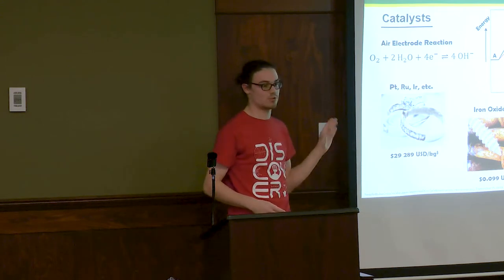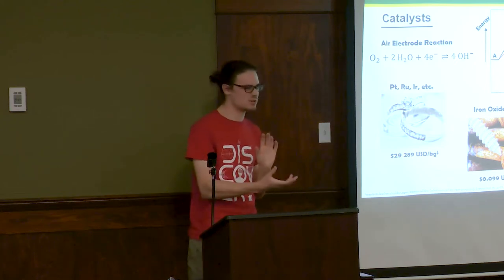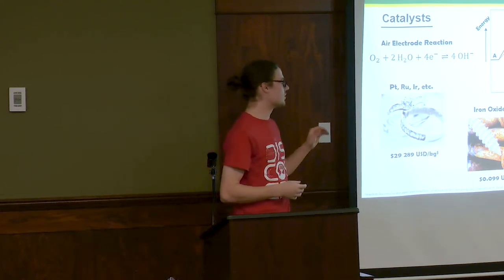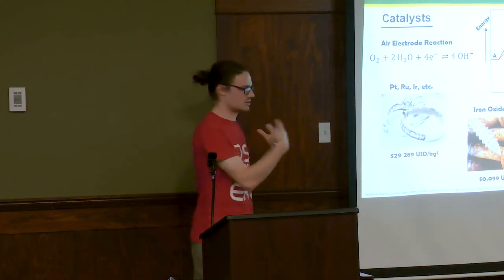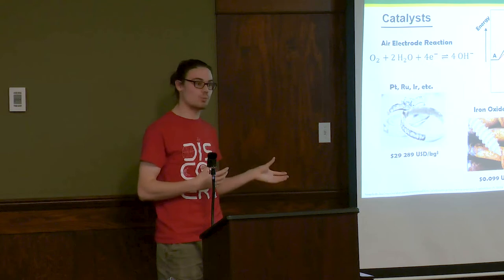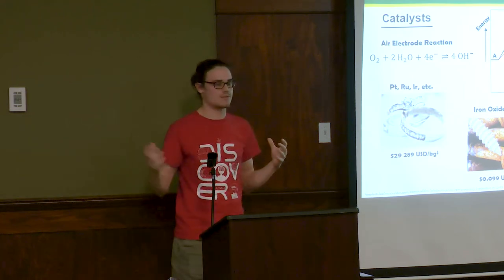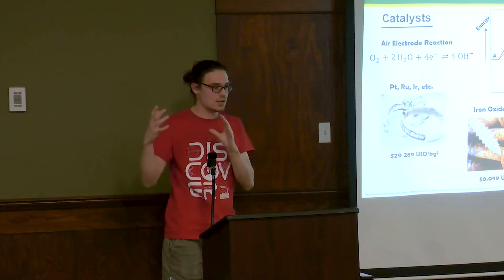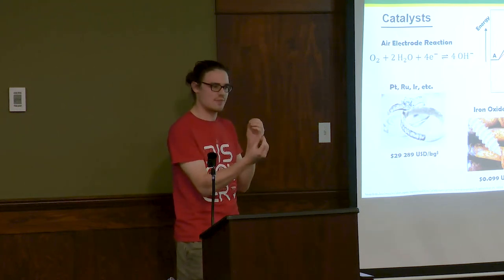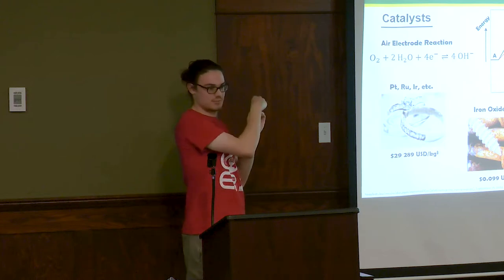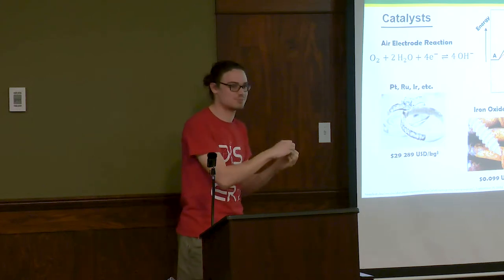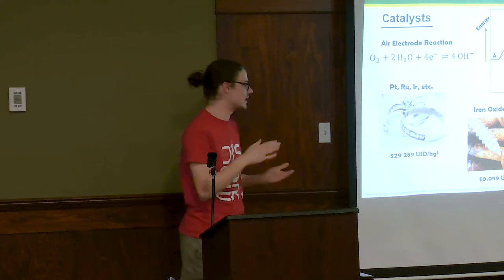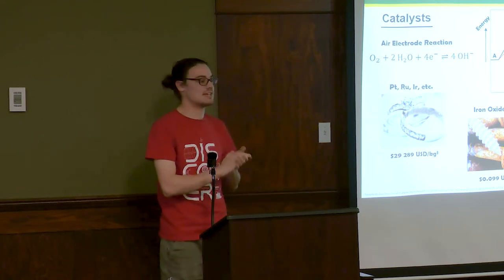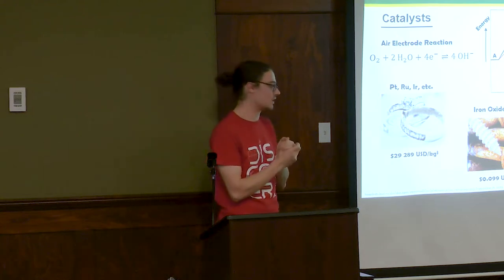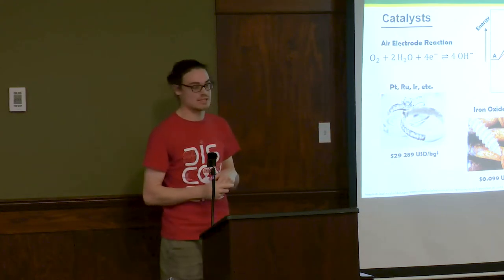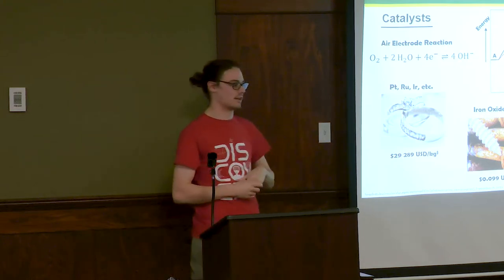Now, cobalt is being used right now with lithium ion. And it's got problems with resources and trying to get it. But zinc is abundant, right? It's also the zinc-air battery. And other people in my group who work on zinc-air batteries found that when we cycle it after about 100 hours or whatever, long tests, what happens is there's zinc in the electrolyte that makes its way into the catalyst and makes it a zinc-based catalyst. So I thought, what if we just add it in the first place? And so that's what I'm working on right now, is deliberately adding zinc to the mix and increasing the stability even more. So that's the element I'm looking at, is zinc. But like I said, cobalt also has some activity and nickel as well. So those are the elements that you look at.